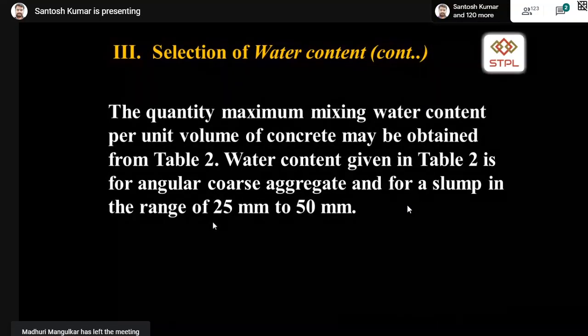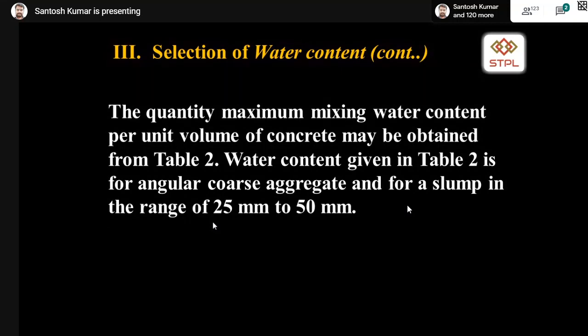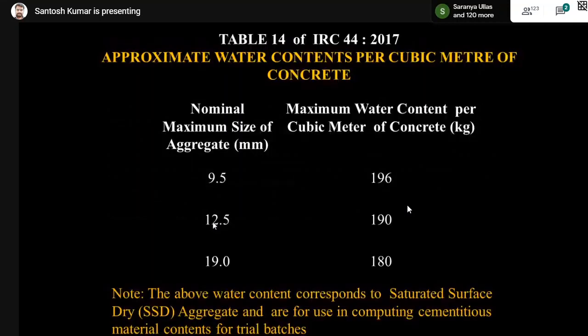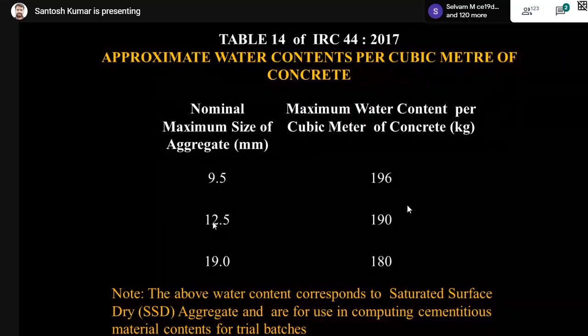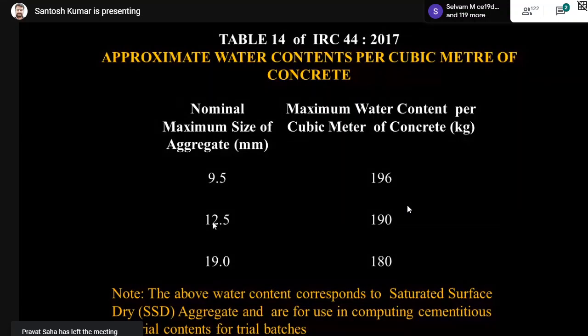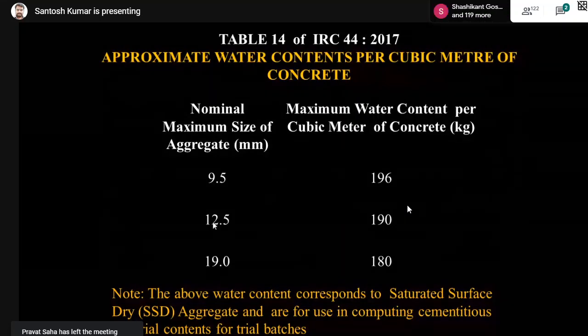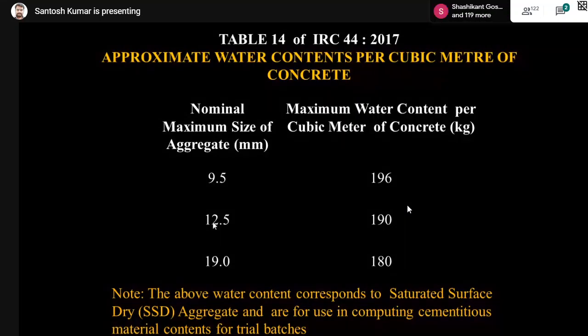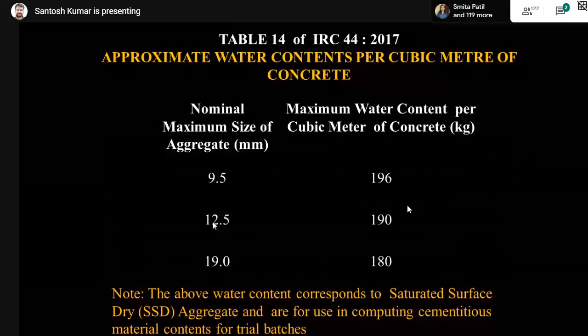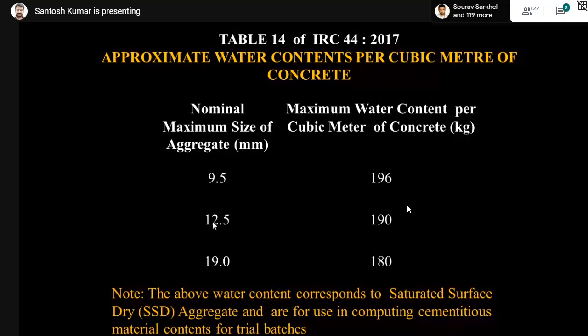The quantity of maximum mixing water content should be as per the table given in the IRC standards. You can see here, this is Table 14 of IRC 44. If you are using 9.5 mm aggregate as your nominal maximum size, the water, when taken in the surface saturated condition of the aggregate, should not exceed 196 kg. In the same case, if you are dealing with 19 mm aggregate as the nominal maximum size, the water content shall not be more than 180 kg per cubic meter.